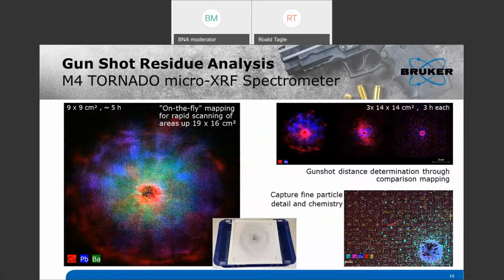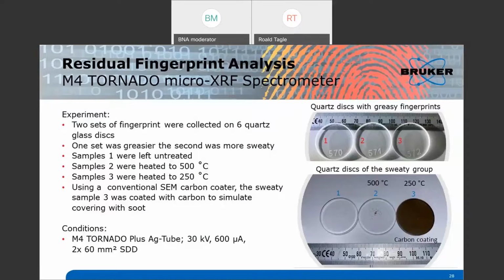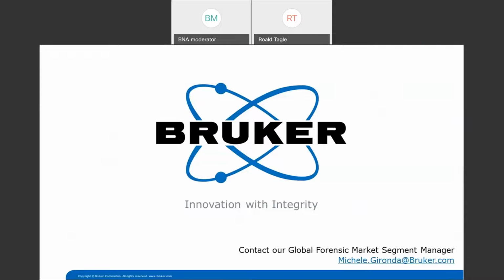And there's also all the physics which comes after the X-rays hit the sample. There is scattering and there is the information depth, and these also limit the spatial resolution. We had a webinar last year where we talked about optimizing measurement conditions for mapping. In it, we also showed measurement series on how the sample thickness defines the minimum spot size you can achieve, significantly. So if you have a sample which is 50 micrometers thick, you have a limit to the spot size which is not based on the quality of your lens. So basically, spot size and maximum resolution depend not only on the spot size of your instrument, but also on the material you are analyzing. It's a combination of these two things that gives the maximum resolution you can achieve with the instrument.